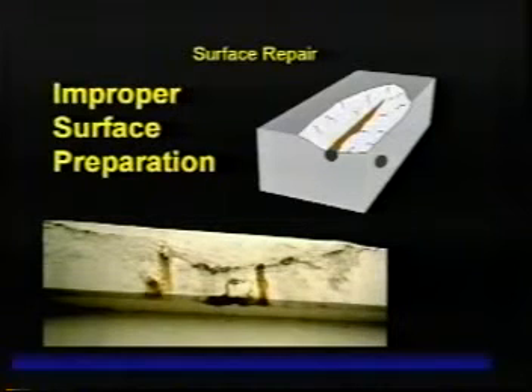One of the things that we highly recommend is that you don't do what was done in the past, which has been shown to create failure, which is just to knock the loose stuff off and apply repair material. I think this is true for all concrete repair techniques. This is not an acceptable method. Since I have 45 minutes, I'm going to try to drill into some of these references on preparation so that you can see the detail that we're recommending.